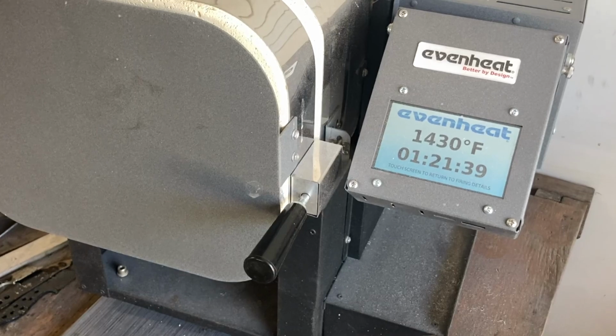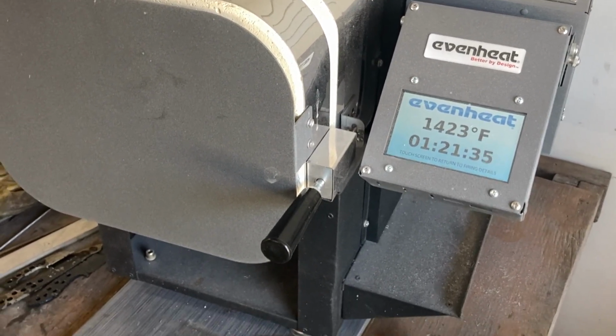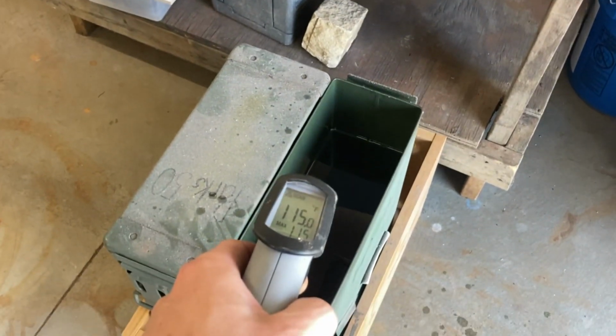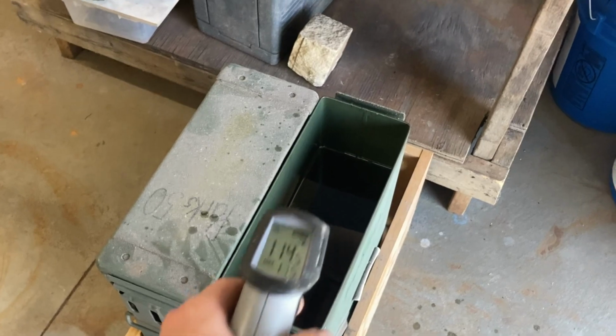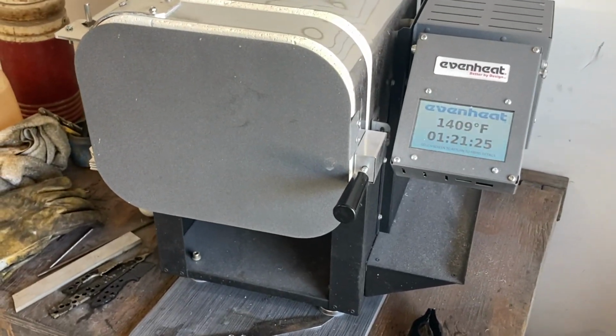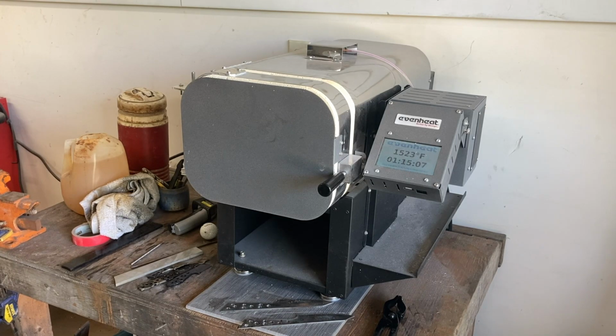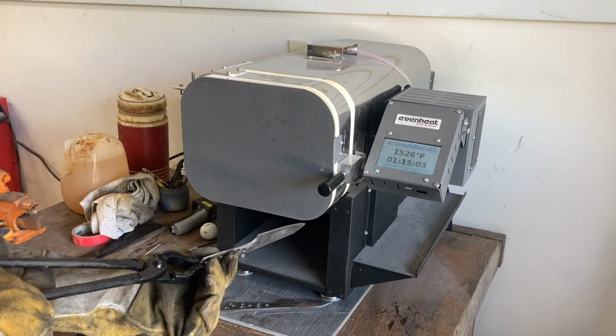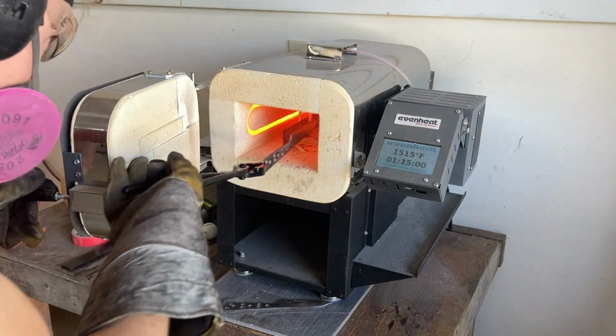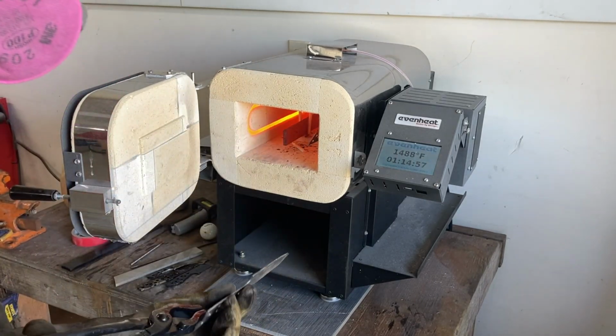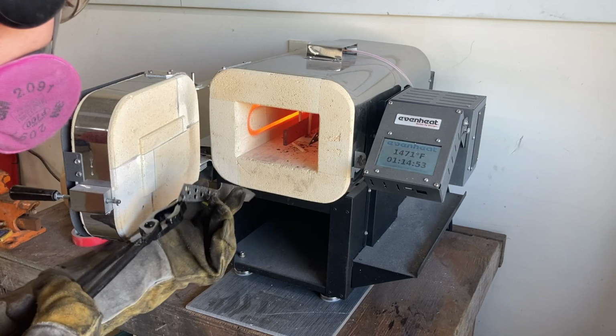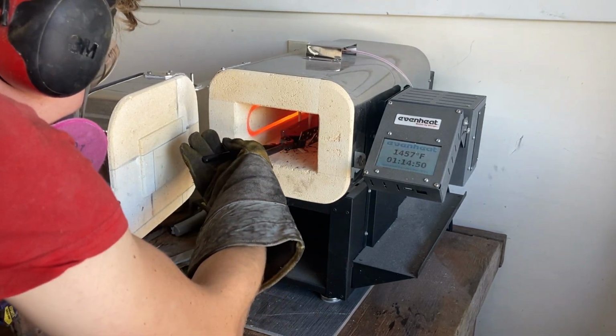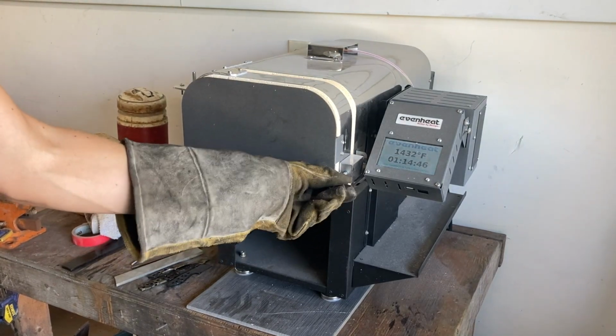Alright, so now that it's time to heat treat these, I have my oven heating up to 1525 degrees Fahrenheit, and I'm also preheating the oil, which is Parks AAA, to around 120 to 130 degrees. And once it's up to temperature, I'm going to go ahead and put the knives in. Now that the knives are in the oven, I'm going to let the oven come back up to temperature, and then I'm going to hold the knives at that temperature for around 10 minutes before quenching them.